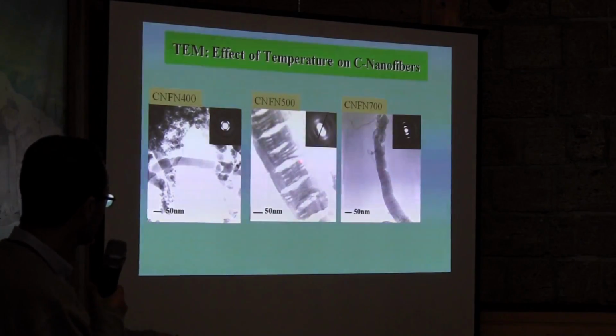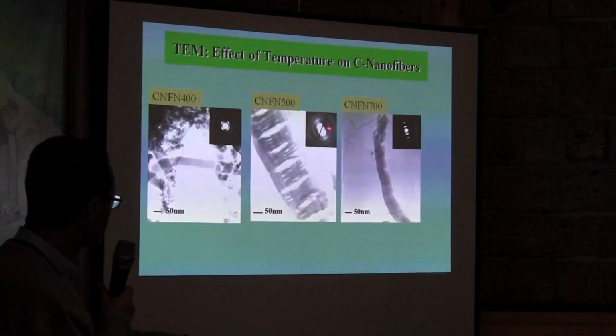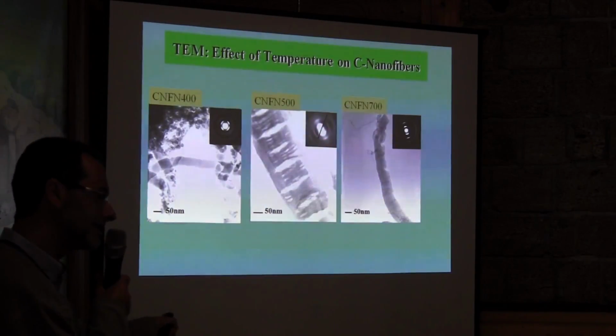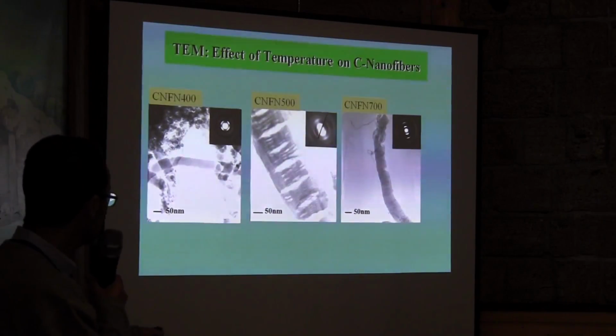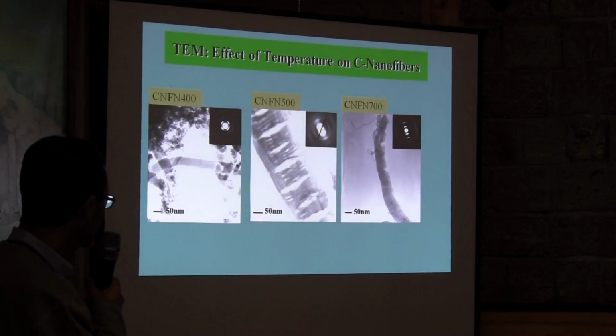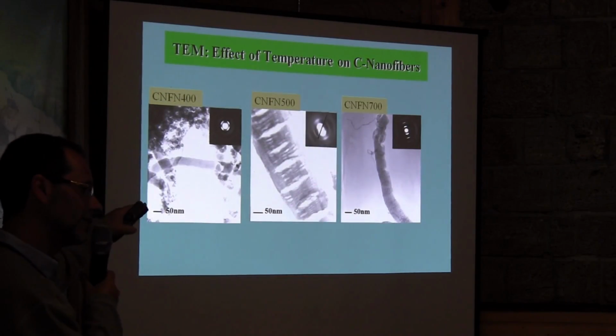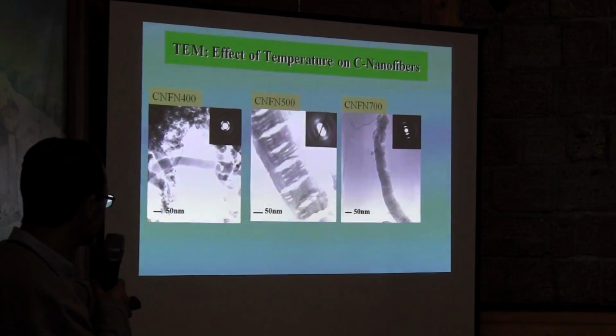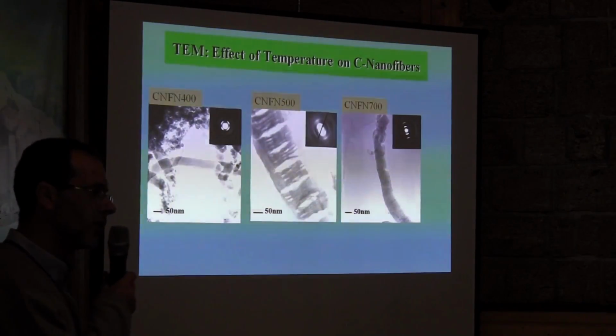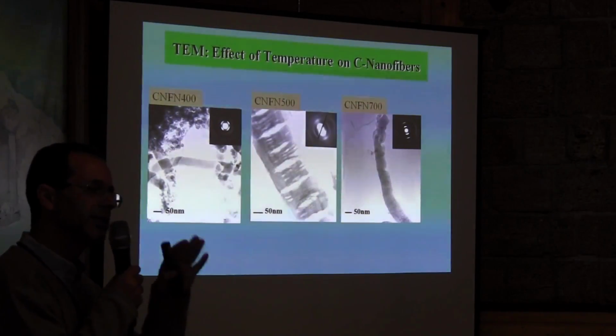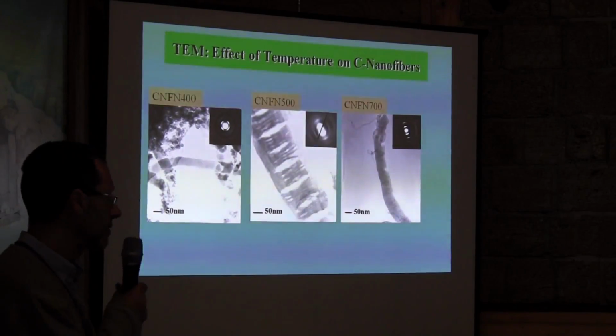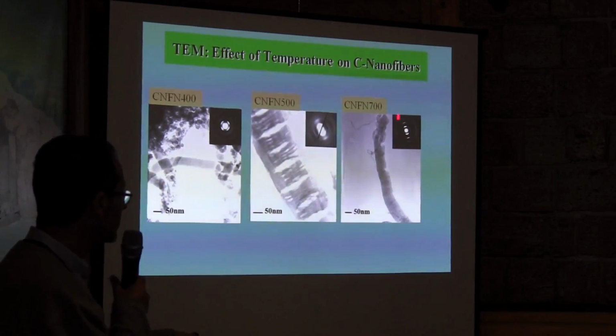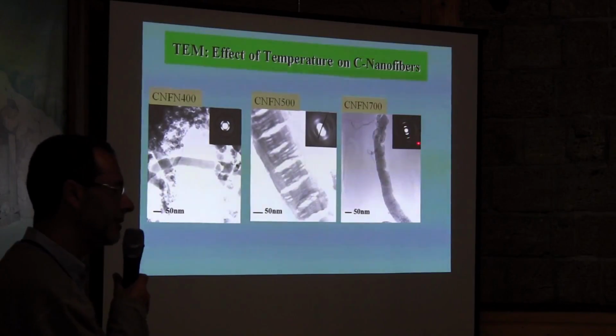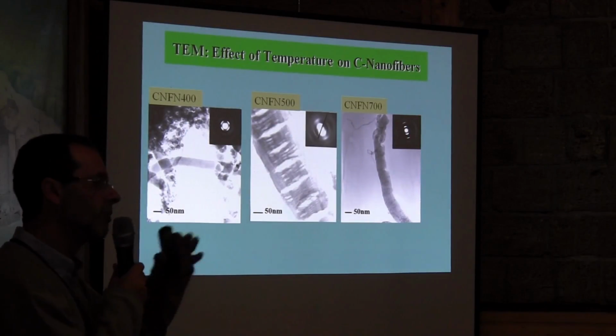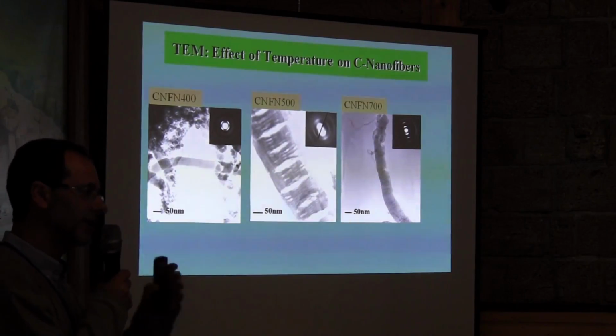If I go to 500, you can see 2 spots, but they are elongated. What does it mean? That means I have aligned carbon layers, but they have so many defects. Why are they elongated? Because there is some amorphous carbon. Now, if I go to CNFN700, you can see the spots are well defined, and because they have more crystalline carbon nanofibers.